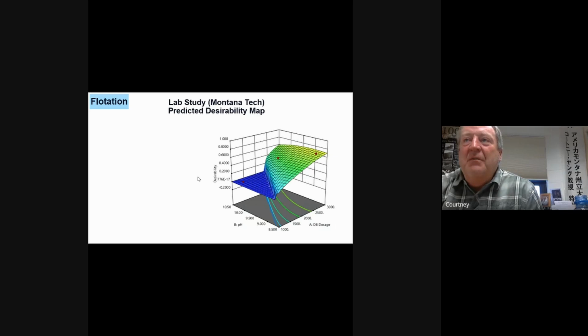So we can take those results and model them with the design of experiment studies. And now we can get three-dimensional plots that show you that, all right, from 8.5 to 10.5, if you're really low in dosage, it doesn't work very well. If you increase your dosage, you start to see a good effect, but it's this little cliff-like profile in here where you see the greatest effect. So you want to be at least greater than somewhere in here where you see this bluish or this greenish color, somewhere in between. And once again, that's that 1100, 1200 D8 dosage range. And your desirability or recovery would increase substantially. This looks like it's up around 70% at a really high dosage at the lower pH. Okay. Again, the magic point somewhere around 1200.